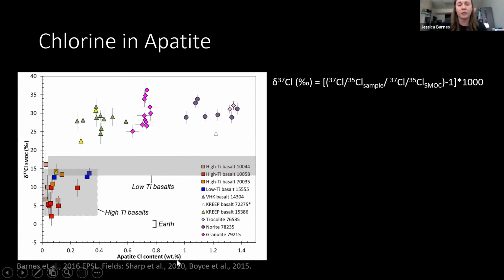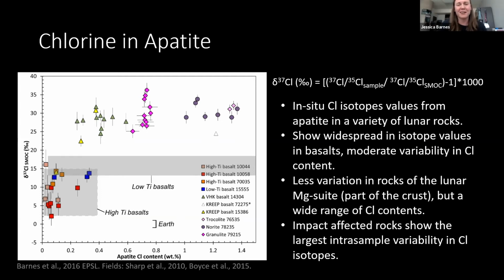This plot is showing you the apatite chlorine content versus its chlorine isotope composition on the y-axis. And you can see, remember, Earth is around here. The chlorine isotope variations in these samples is wild. Our work shows that the in situ chlorine isotopes from apatite vary according to rock type. The largest spread in chlorine content is shown by the crustal samples that show a relatively restricted range in chlorine isotope compositions, except for the pink diamonds, which represent impact process samples. And then you can see, relatively speaking, the mare basalts, the basaltic volcanic samples, they're all plotting at lower chlorine isotope compositions and relatively restricted apatite chlorine contents.